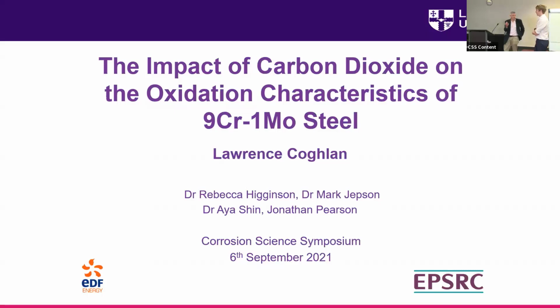Was it an iron-moly core? Is that linked to a metallic or some kind of spinel phase, or is it a carburized sample? What is that core, the one at the end? The M23C6, yeah. What do they grow around? I think that was a prior M23C6 carbide, which when the oxidation front reached it within the substrate, the chromium effectively diffused outwards to oxidize preferentially to the iron, forming the chromium-rich oxide, which is effectively just the chromium-rich spinel layer, which is what gives the 9-chrome steel its oxidation resistance to start with, but just more concentrated in that area.